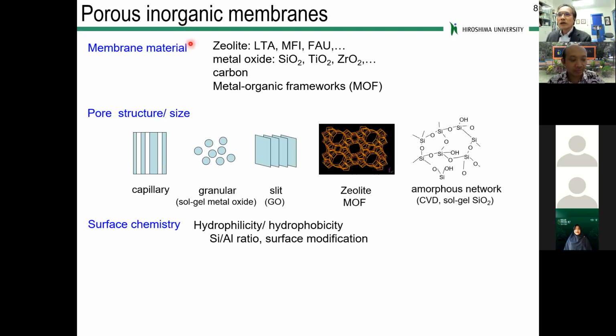Porous inorganic membranes can be categorized based on membrane materials as zeolite, including LTA, MFI, faujasite membranes, and also metal oxide, silica, titania, zirconia, carbon, and metal organic frameworks. These membranes have different types of pore structure, like capillary type, granular type, especially typical for sol-gel-derived metal oxides like silica and titania, and also slit-type pores of the carbonized graphene oxide, while crystalline materials are zeolite or MOF-type membranes. Amorphous networks are like this, prepared by CVD or sol-gel silica-type membranes.